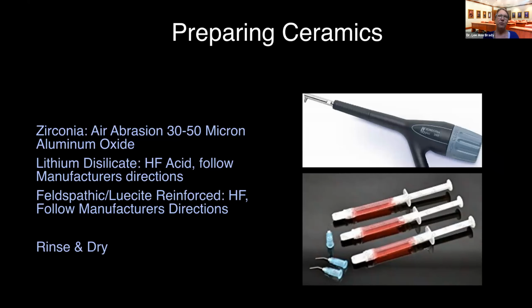How do we prepare zirconia? Zirconia restorations can only be prepared, or the word etched is what we use, with 30 to 50 micron aluminum oxide. There is no liquid chemistry that etches zirconia for now. There's one trying to get through FDA approval, but at the moment, there is no liquid or chemical that actually etches zirconia. 30 micron aluminum oxide, 1 bar of pressure, which is 15 PSI. And so it's a pretty specific etching protocol.